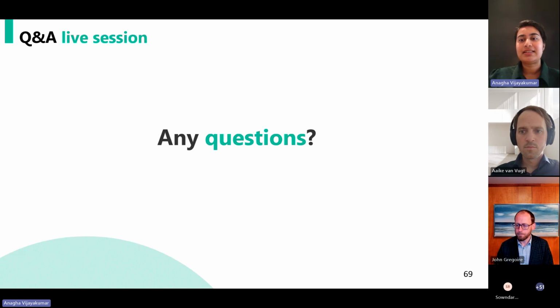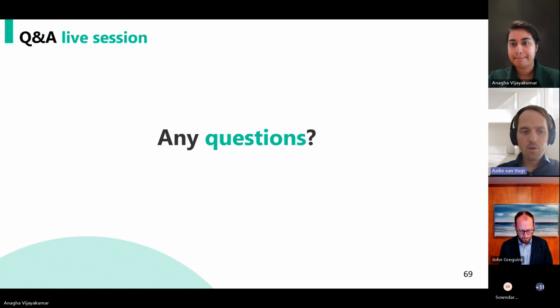Thank you. And Hannah also has a question to Aaike. Can the sample be heated and is it limited to metals? So there is currently no heating capability of the stage. That's definitely something we are considering. The sample can always be taken out and put into an oven, if that is the question. I just want to mention that when you are printing the material, the gas is almost at room temperature. So there's almost no elevated temperature upon printing. Again, the spark is at very high temperatures, but the moment the nanoparticles are exiting the nanoparticle source, the temperature is already down at room temperature because of the continuous inflow of carrier gas at room temperature.